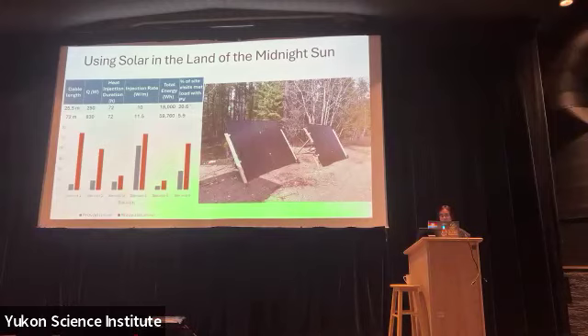With the 25.5 meter cable, I was able to meet the instantaneous load about 20.6% of the time. So on my site visits every 4 to 6 hours when I show up, is my solar energy matching my heat output? That's happening about 20.6% of the time. With the 72 meter cable, I was only able to meet the instantaneous load about 6% of the time. So that means I've had to run the backup generator almost constantly in order to meet the needs of that load. However, this year I doubled my solar capacity.